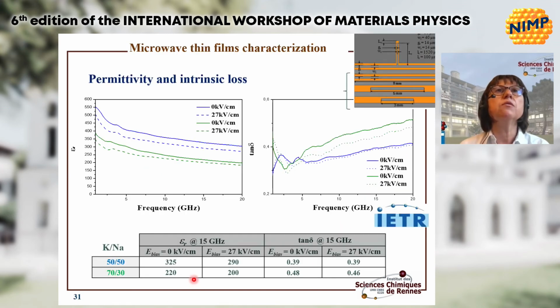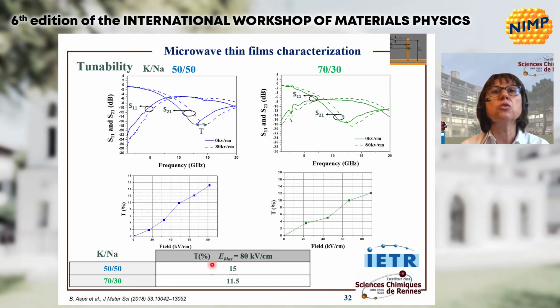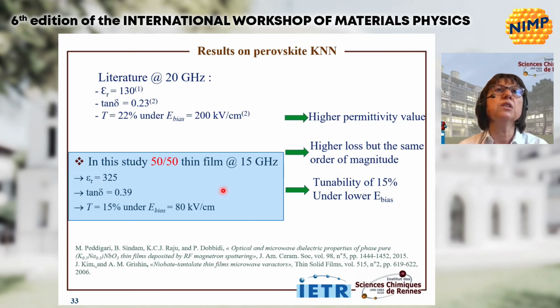After that, dielectric permittivity and intrinsic loss have been measured at high frequency. And we can see here that for the two compositions, the permittivity has been compared. The highest permittivity is obtained for the 50-50 composition. Then tunability has been measured. The losses, tangent delta, are more or less the same, even higher on the 70-30 composition. And we can have a look at the tunability, that means measurement without and with an electric field. The values of the permittivity and the tunability on both compositions show that the tunability is higher on the 50-50 composition. After that, we have worked mainly on this composition, 50-50, potassium over sodium.